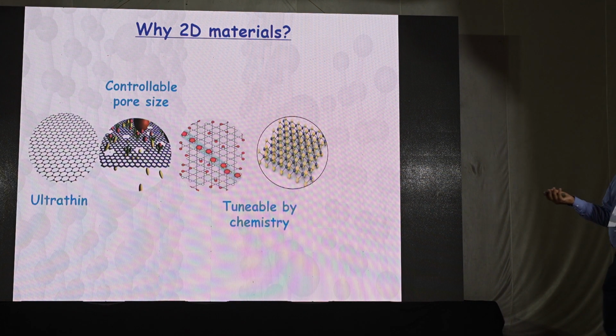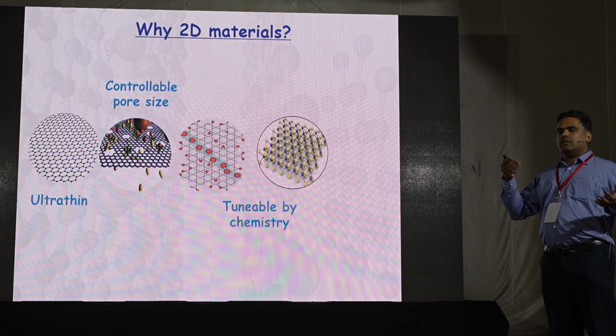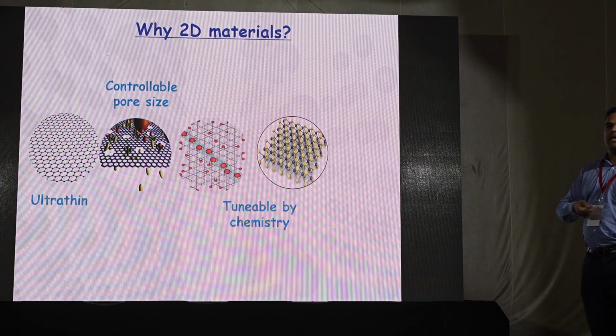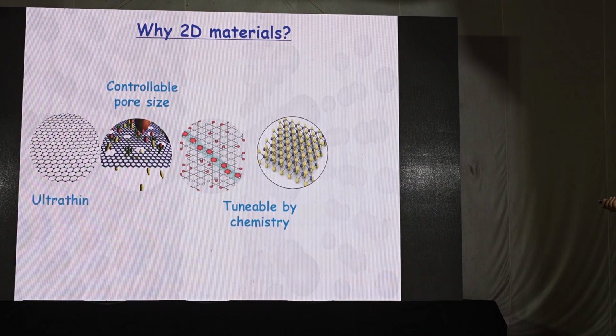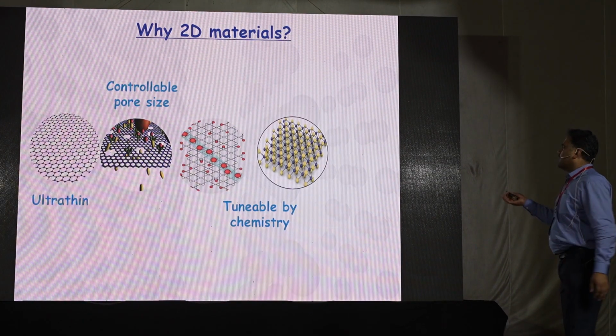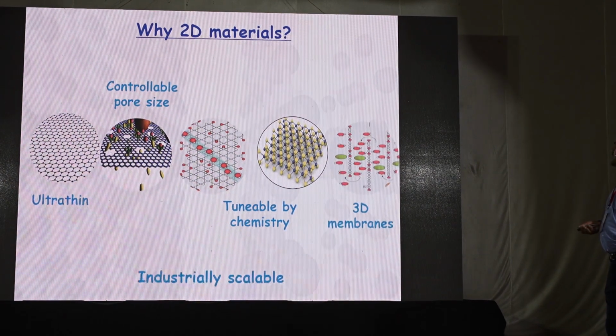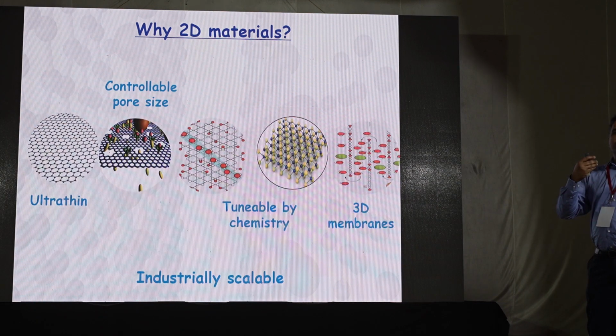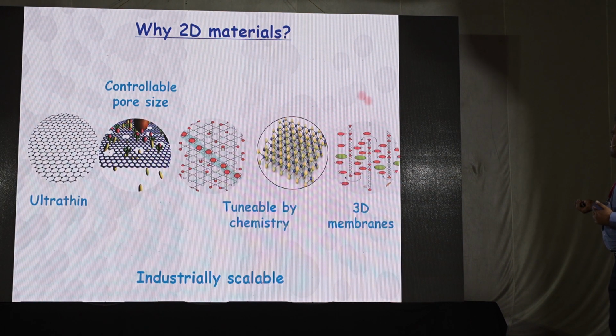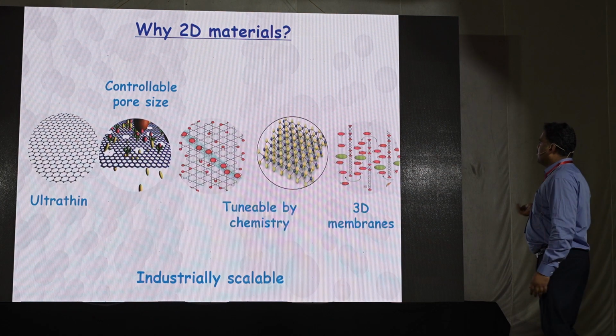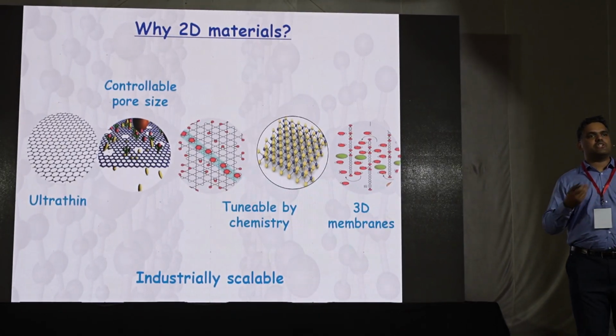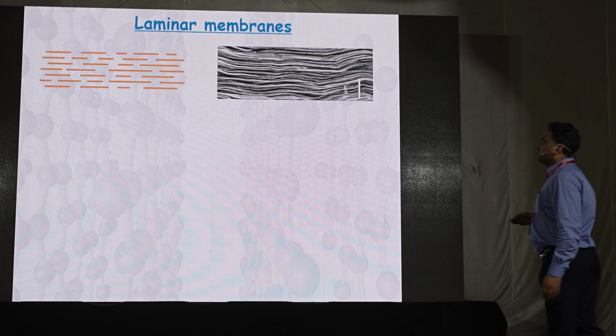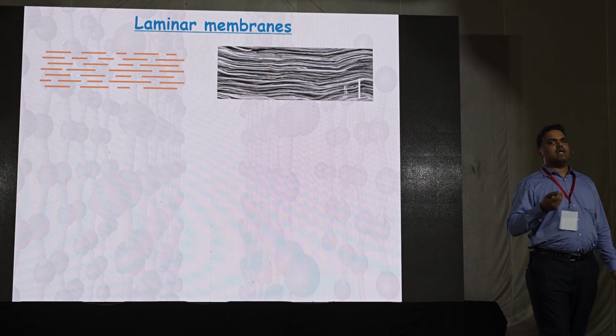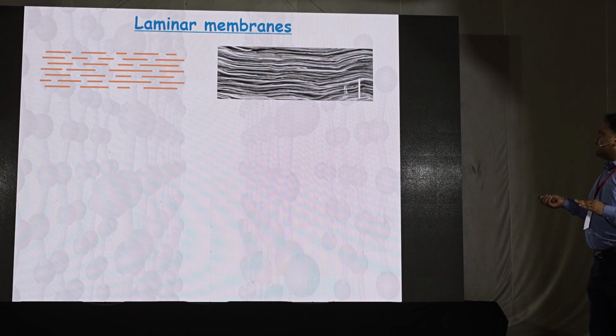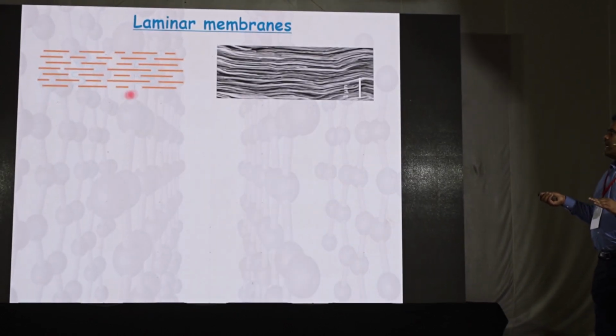You have even more flexibility. You can chemically modify this material, or you take graphene with molybdenum disulfide or tungsten disulfide, any property you can modify chemically. You can get different hydrophilicity, hydrophobicity, oleophilicity, everything you want you can create by chemical functionalization. And last but not least, not just 1 atom thick. If you really want to use this membrane in the real field, you can even make a 3D kind of membrane by stacking these 2D materials into a paper-like material that we call a 3D laminar membrane for designing scalable, industrially usable membranes. So in my group at Manchester, we are primarily working on laminar membranes. A laminar membrane is not just a 1 atom thick membrane. So what we do is, you take several one atom layers and stack them on top of each other.